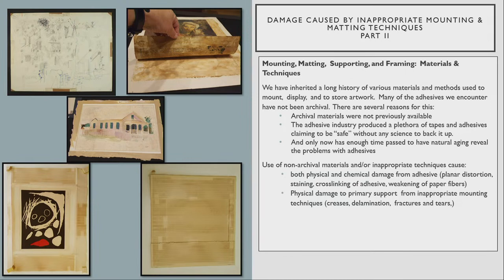First, there's both physical and chemical damage from the adhesive, planar distortion, that means there's cockling in common speak. There's staining, there's cross-linking of adhesives, and cross-linking means that the adhesive, which typically sits on the surface and makes an adhesive bond, as it ages, gets into the paper fiber as a chemical reaction and bonds with it, so it becomes much more difficult, not impossible, but much more difficult to separate the adhesive out of the paper. And if you don't remove the adhesive, then it will destroy that area where the adhesive tape was. And then physical damage to the primary support from inappropriate mounting techniques. These can cause anything from creases to delamination to fractures and tears.